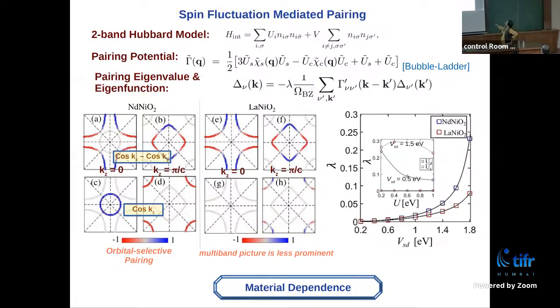And then the interaction: the calculated electron-phonon coupling is actually small, so we didn't consider any phonon mechanism. Instead, we had a correlated mechanism. We had an interaction term U between x square minus y square and x square minus y square, axial and axial. But we also had a V term, connecting the x square minus y square and the axial. That's an interorbital interaction term. And within the RPA, by summing up the bubble and ladder, we could write the pairing potential, and then the superconductivity problem was solved through a self-consistent equation, where delta is nothing but the superconducting wave function, which is basically the strength of the pairing.